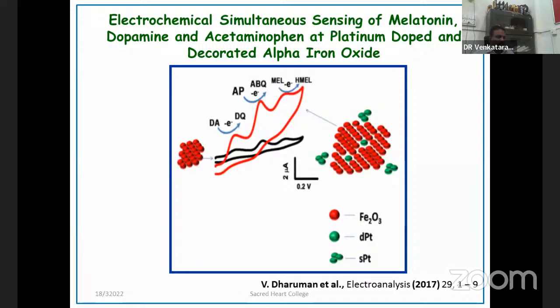Here we prepared iron oxide by the hydrothermal method, and it is doped with platinum. This doping was done by physical adsorption, where most of the platinum is attached on the surface. Because the whole material is subjected to thermal annealing, sometimes it may diffuse into the interstitial sites, which we call interstitial doping, and we try to monitor the signal.